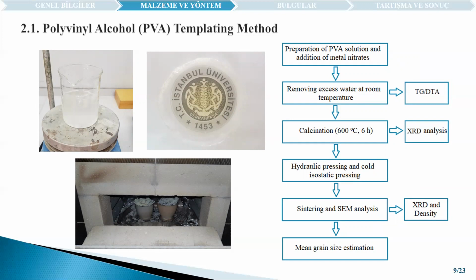After that, the solution was poured into a thin film and allowed to dry at room temperature. A transparent and flexible film was achieved and calcined at 600 degrees for 6 hours. During calcination, the PVA matrix burned off and pure ceria powders were obtained. Powders were ground in an agate mortar and pressed into 10 millimeter diameter pellets. These pellets were sintered at 1200, 1300, and 1400 degrees for 5 minutes, 1 hour, and 6 hours each. This way, we tried to understand the effects of sintering temperature and sintering time on the product.